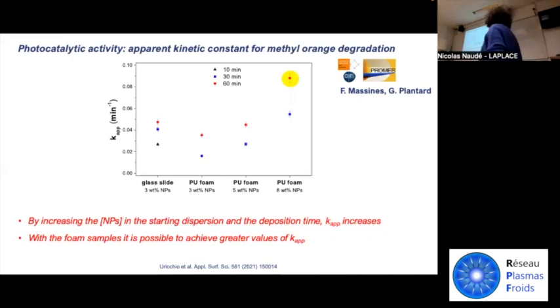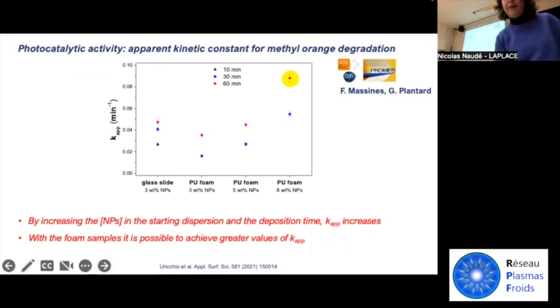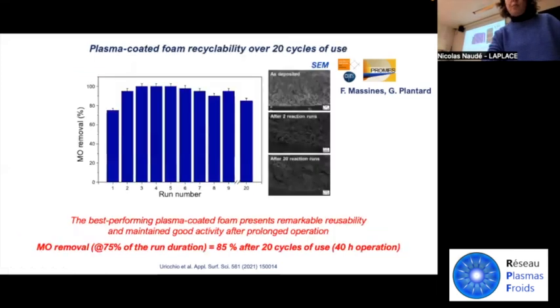So we observed that for both types of samples, by increasing the nanoparticles concentration in the starting dispersion and the deposition time, it is possible to obtain an increase of the apparent kinetic constant. But in general, with the foam, it is possible to achieve greater values of apparent kinetic constants. And there are also other parameters that could be explored to further increase the activity of the plasma coated foam.